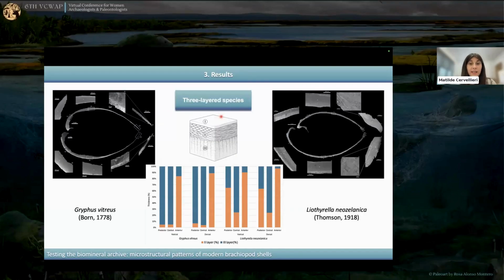Now we see the results for the three-layer species. So in addition to the first two layers, they also biomineralize a columnar tertiary layer. And we have two three-layer species, Gryphus vitreus from the Mediterranean Sea and Liothyrella neozelanica from New Zealand. They are quite comparable in their central region and anterior region. In the central region, we have, for both of the species, a huge block of columns, whereas in the anterior region, the tertiary layer is decreasing until disappearing, and we have the secondary layer dominating over the tertiary.